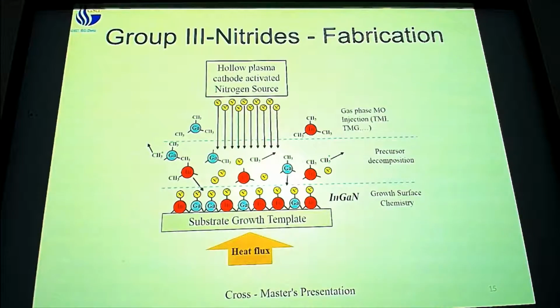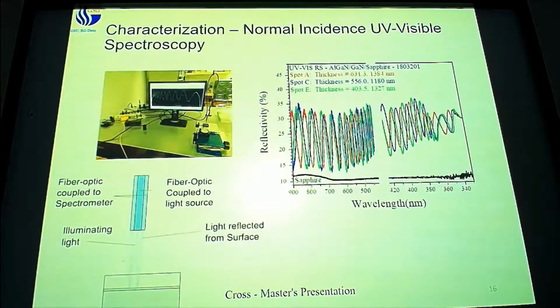We still have a slightly high temperature where the gallium or the indium nitride can decompose at this point. This system is mostly used for indium nitride. But we have this high temperature region where the TMG or TMI can decompose, and they combine with the nitrogen ions from the plasma instead of from ammonia. And they can then form on the surface and grow the material on the surface.